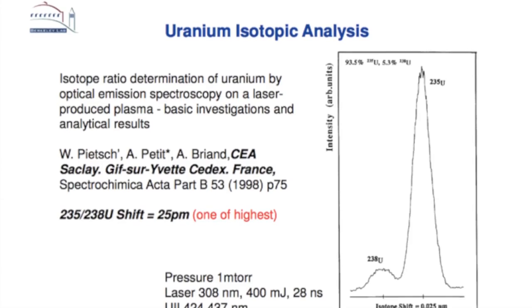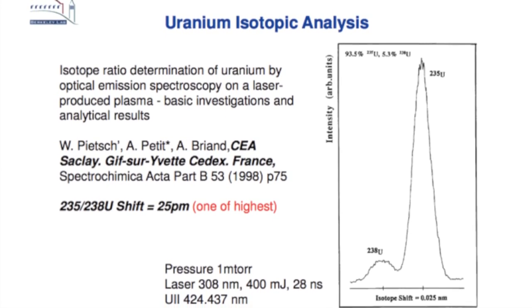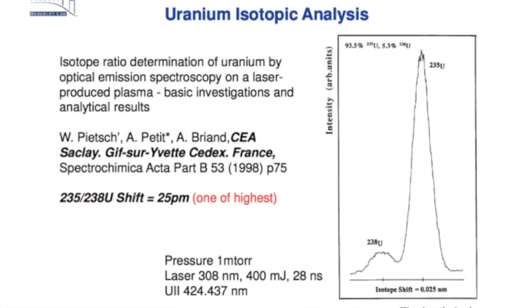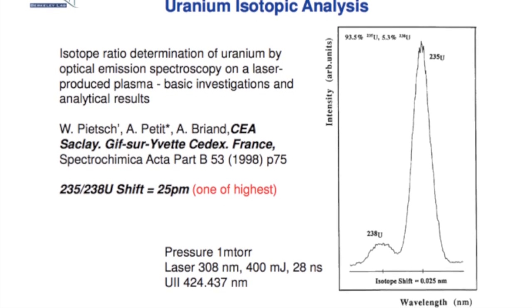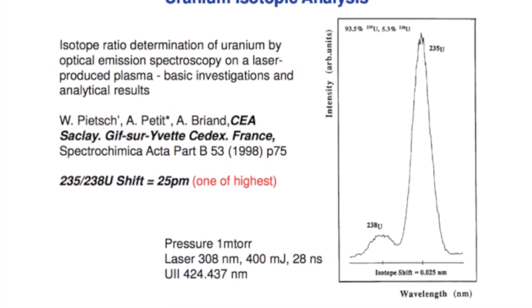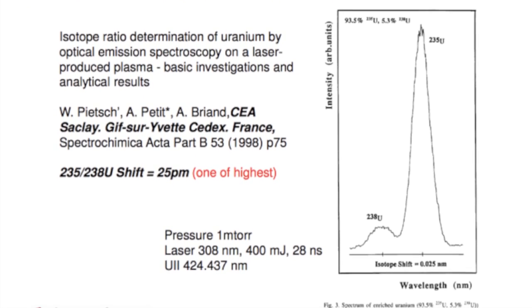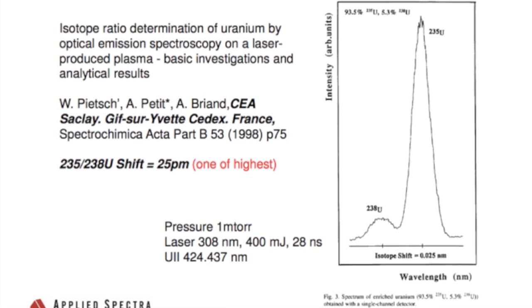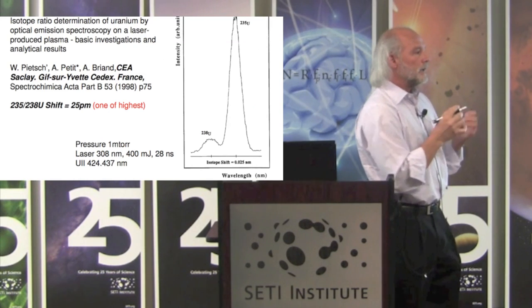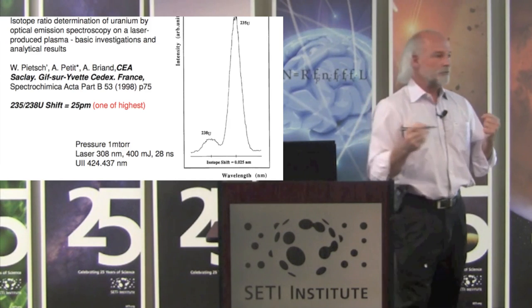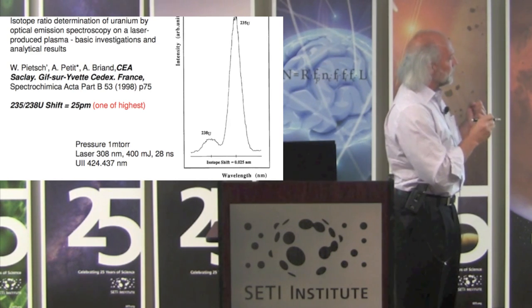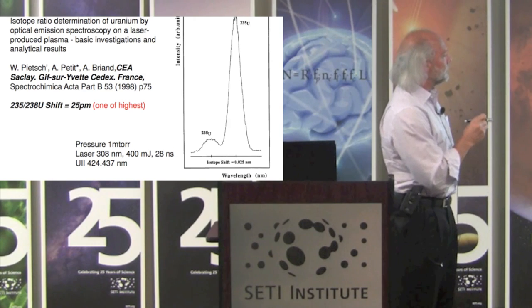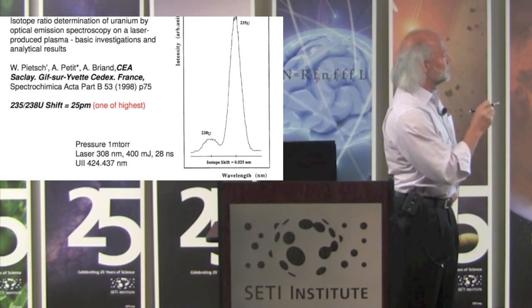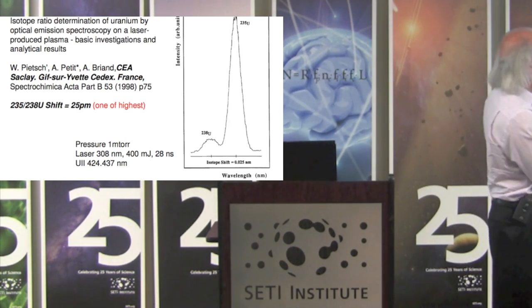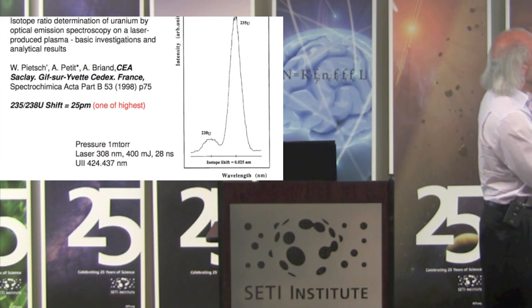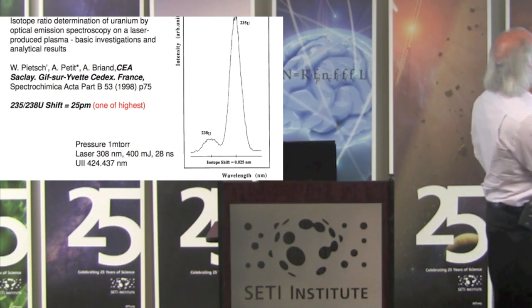This is just some other work where uranium, so Los Alamos did some work back in the early 90s where they did show you could do isotopes in these laser plasmas, but you had to have a reduced pressure and an inert environment, because you had to cool the plasma and you could not have collisions. You had to get the electron number density down. At this low pressure, with the laser they used, they were able to see the ratio of 235 to 238 in this highly enriched uranium.